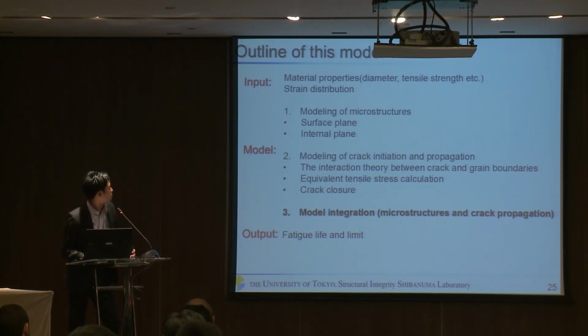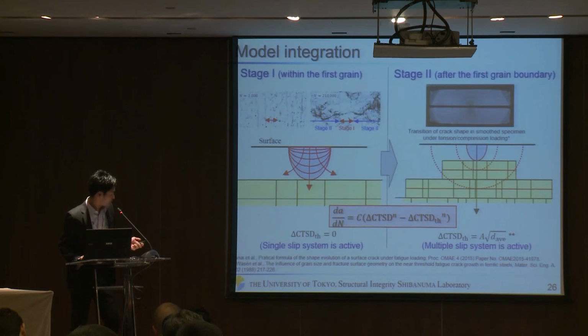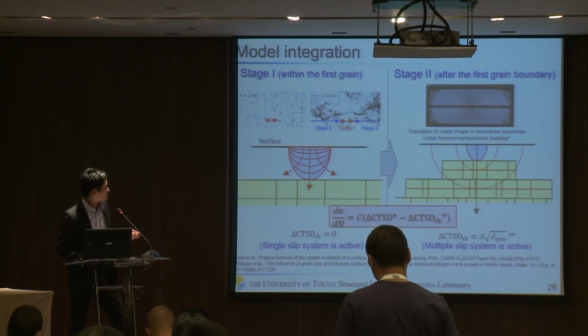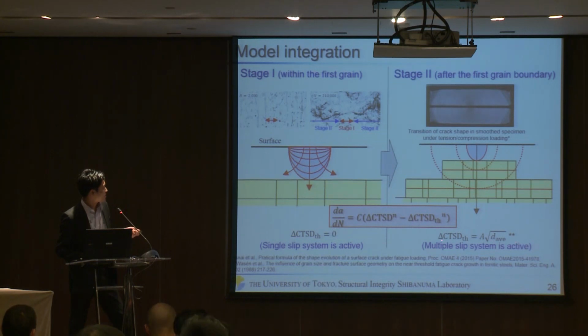Okay, so model integration. As I explained, stage 1 propagates in the first grain, and stage 2 propagates over grain lines. So in this model, these stages are combined, and the threshold is shown like this. In stage 1, it's 0 because a single slip system is active. But in stage 2, the threshold is this value because multiple slip systems are active.